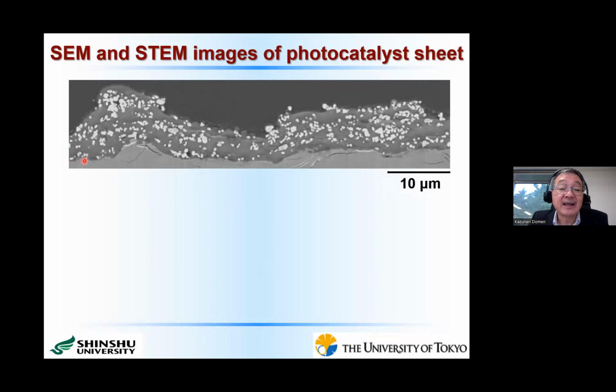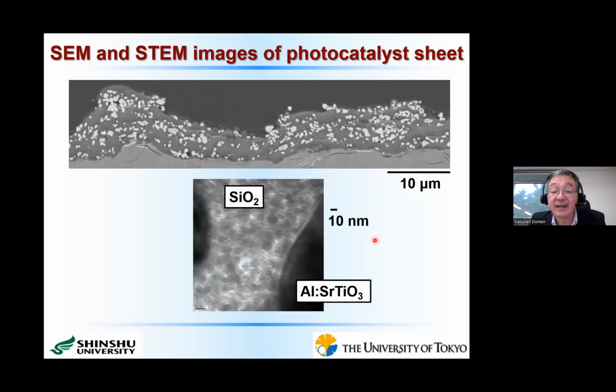We use, in this case, frosted glass. So the surface is curved like this one. Then these white particles are photocatalyst, and this dark gray part is nano-sized silica particles. Then this is a more magnified STEM image. This is the 10 nanometer scale. And this black part is the aluminum-doped strontium titanate photocatalyst, and these are the nano-sized silica. As you see here, the particle size is about 20 nanometers.